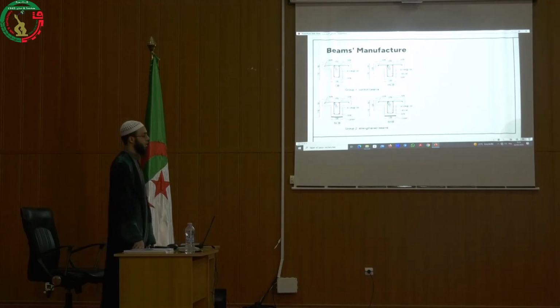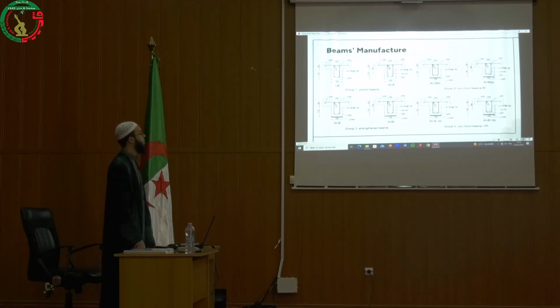Our tested beams were divided into 4 groups. The first is the control beam, which was not strengthened in the tension zone. The second is the strengthened beams, which were strengthened by 1 CFRP laminate on the tension zone. The third is the preloaded beams, loaded to 80% of the ultimate load of the control beam and after that retrofitted by 1 CFRP laminate on the tension zone. And the last group is like the third one, but in this case, the beams were loaded to 100% of the ultimate load of the control beam.